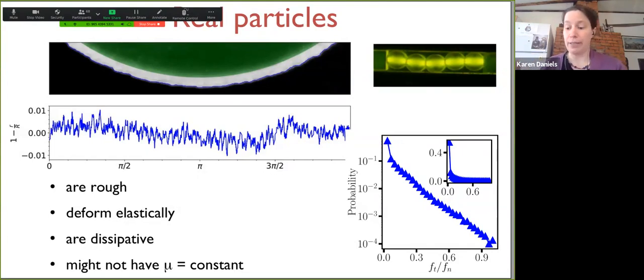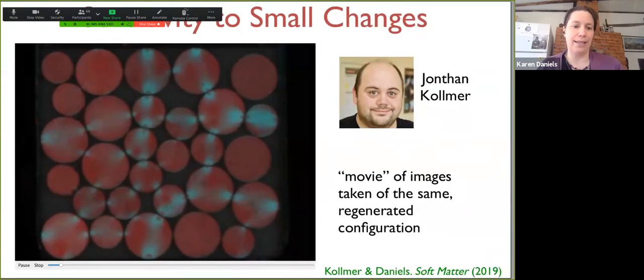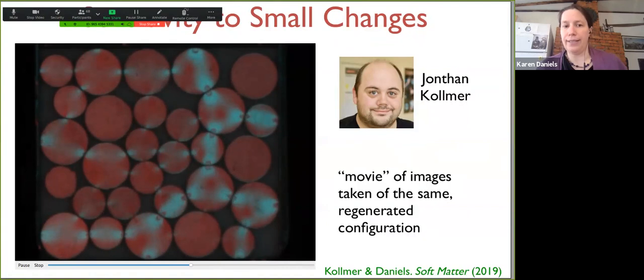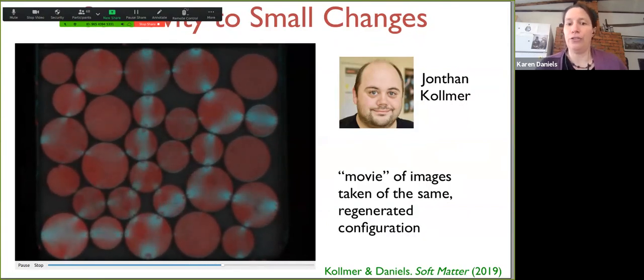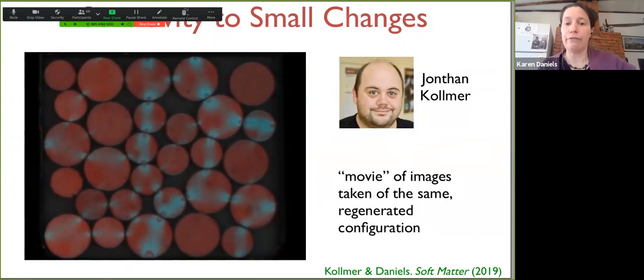And if you do the same experiment over and over again, you don't get the same answer. These are not perfect. So this is, I'm going to say, a movie in quotes, because it's actually just a bunch of still images from my former postdoc Jonathan Kollmer, now in Duisburg in Germany. He made the same configuration over and over, and it's never quite the same. And this is due to the history of frictional loading. It's due to different disparities, and this is sensitivity to initial conditions, even if they were perfect. So there's a lot of richness in these systems, even though they seem fairly simple.